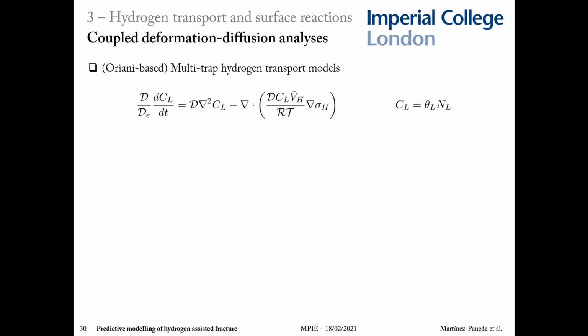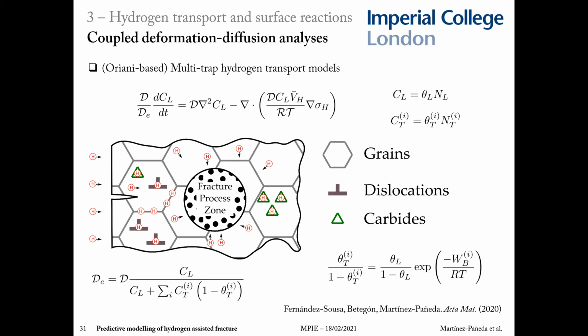So let me jump to the third research front, the chemistry. Hydrogen diffusion is normally characterized using an extended version of Fick's law, as you see in the slide. Note the important role of the hydrostatic stress, as I mentioned before. So there's a strong coupling with the mechanics. And one thing that we have been working on is the development of multi-trap models, as hydrogen atoms can be trapped at microstructural features such as grain boundaries, dislocations, carbides, and this affects diffusion. So it's something that you may want to incorporate in your modeling depending on what you're looking at.